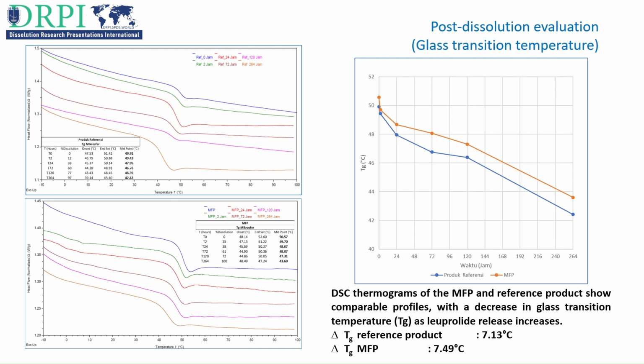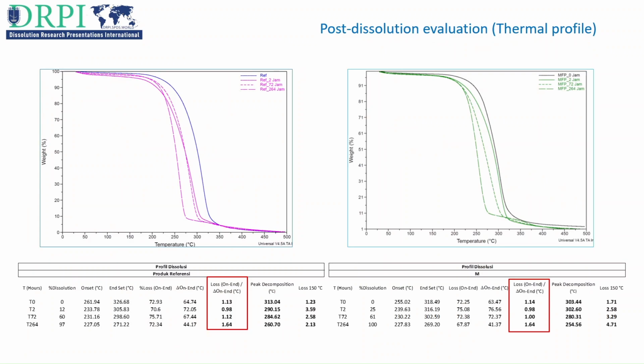The DSC thermograms of the final microspheres and the reference product showed comparable profiles during dissolution testing, with decreasing glass transition temperature as leuprolide acetate release increased. The reference product showed a glass transition temperature decrease of 7.13 degrees Celsius, while the final microspheres showed a decrease of 7.49 degrees Celsius. And last, TGA thermograms of the final microspheres and the reference product showed comparable profiles with weight loss rate increasing alongside leuprolide acetate release.